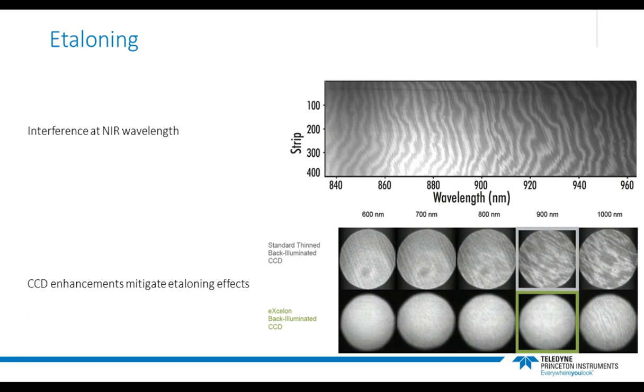And this effect is known as etaloning and leads to these irregular interference patterns in the detected data, as can be seen in an image from such a device on the top right on this slide. However, skillful manufacturers have the ability to enhance the sensors before they are put into a camera to mitigate these effects. So on the bottom right, you see images comparing a standard back illuminated CCD to one of those enhanced devices in the NIR region. And so you can clearly see the effect of this enhancement and how it improves these interference properties.